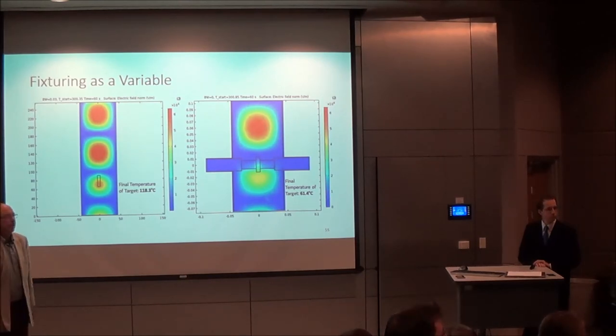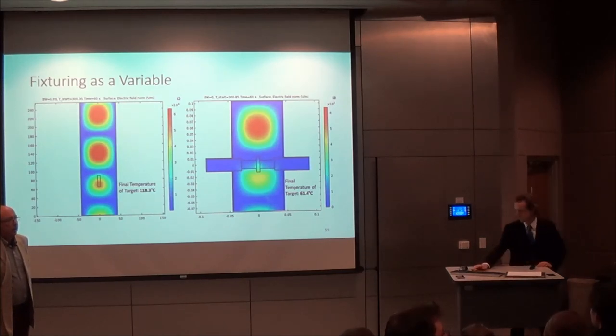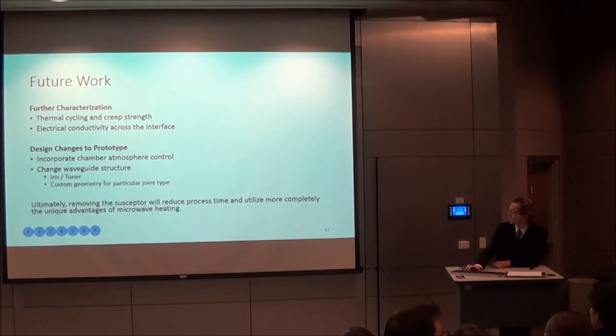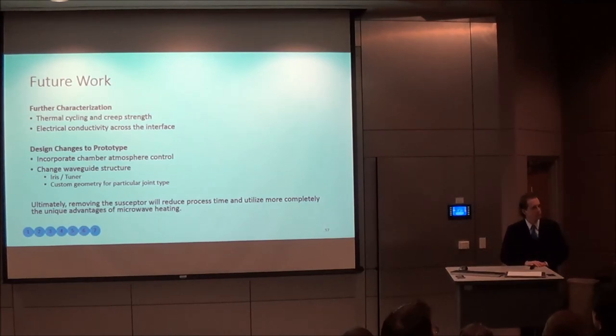At the very end of your conclusions, talking about future work, you talk about removing the susceptor, again, altogether. And from your thesis work, it looks like the susceptor was the key to actually getting sufficient heating. So how is removing the susceptor going to actually reduce process time? Because there's a latency introduced by having to transfer heat from the susceptor to the joint. I mean, fundamentally, if the heat's not being generated in the actual interlayer itself, the time it takes for that heat to get to the interlayer is going to add time.